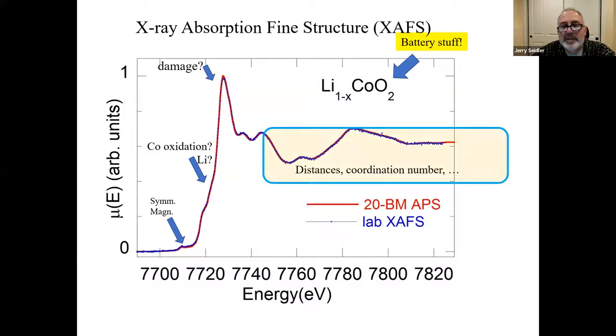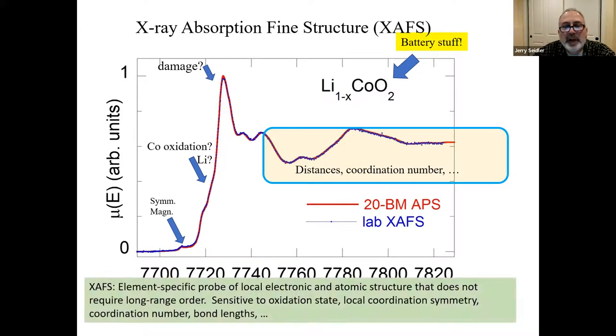And these oscillations that continue quite far in energy, if you're lucky, can be used to infer distances to nearest neighbors and sometimes beyond, coordination numbers and so on. So in general, XAS is an element-specific probe of your local electronic and atomic structure that does not require long-range order. So quite distinct from diffraction, and has sensitivity to oxidation state, local coordination, symmetry, and bond lengths, and so on.